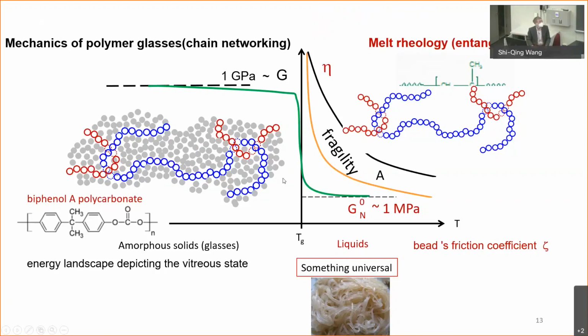So with that language, I'm indicating the first three factors: physical aging. Oh, that's just your gray dots moving closer to each other, packing better. With pressurization, again, you're just trying to squeeze them together even better. Okay. Third one, remember the magician's game, go through the two-roll mill and it turns ductile.